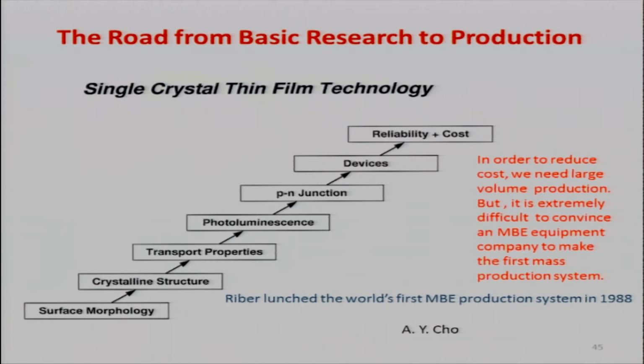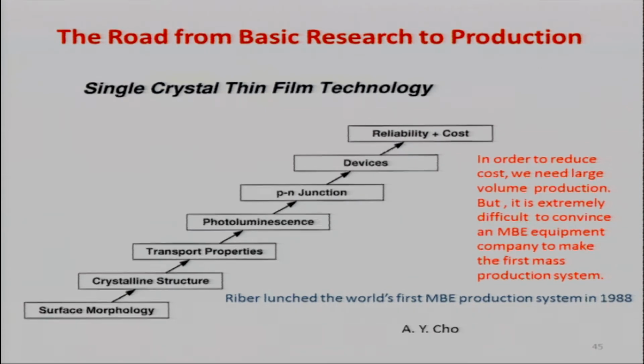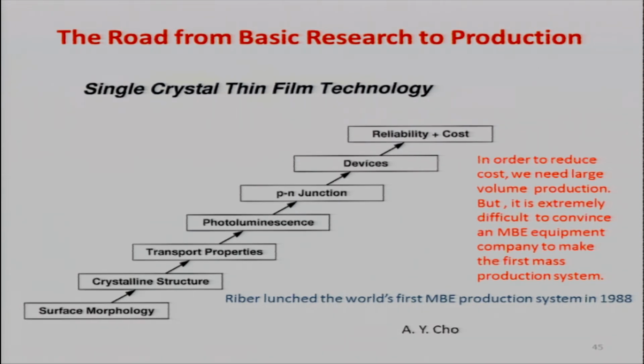For crystal growers like us, we first grow a layer, we look at the surface morphology, take a picture with a Nomarski camera, and then we publish paper. And then next difficulty is the crystallinity of the structure. Are you polycrystalline? Are you a single crystal? Is there a defect in there? And then next level up is transport properties. After you grow a crystal, you measure mobilities. The mobility can be terrible because of traps and all the other things in there. You had to grow very high quality materials, purity, to grow high mobility devices.